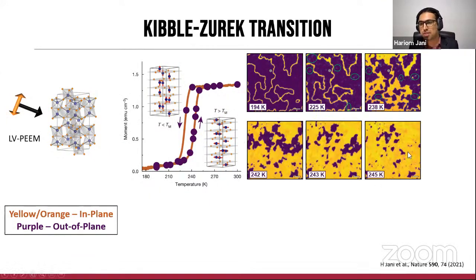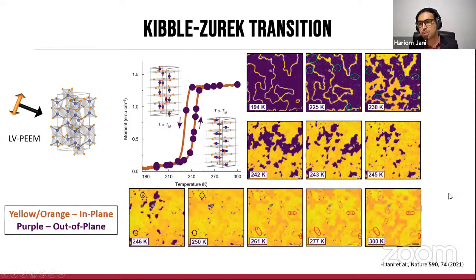Now, as we further warm the system closer and closer and across the transition, we start to see emergence of greater yellow-orange and smaller purple, until at the highest temperatures we have predominantly yellow-orange. But now the curious feature is that there are many purple dots or little bubbles observed in this image here, which persist all the way up to room temperature, far above the Morin transition in the sample, which happens to be around 240 Kelvin in these thin films.